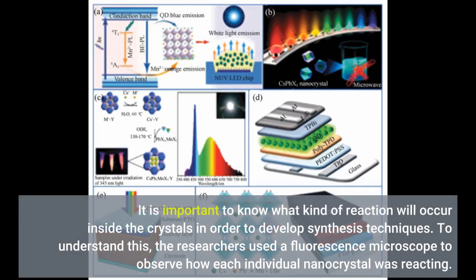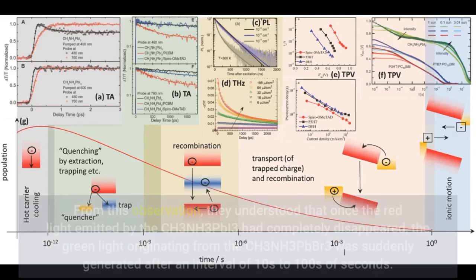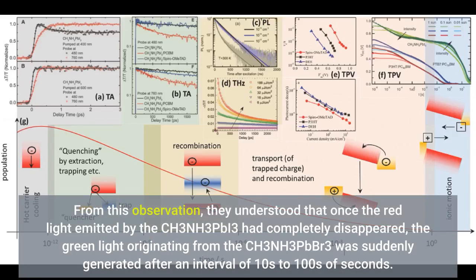It is important to know what kind of reaction will occur inside the crystals in order to develop synthesis techniques. To understand this, the researchers used a fluorescence microscope to observe how each individual nanocrystal was reacting. From this observation, they understood that once the red light emitted by the CH3NH3PbI3 had completely disappeared, the green light originating from the CH3NH3PbBr3 was suddenly generated after an interval of tens to hundreds of seconds.